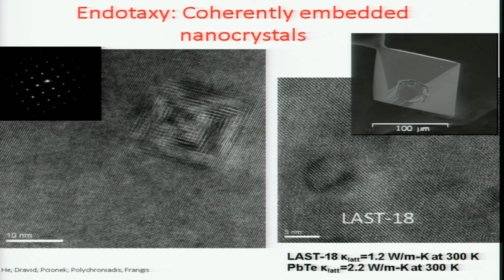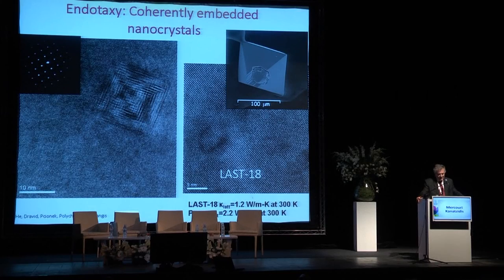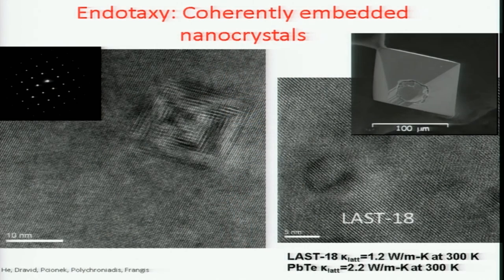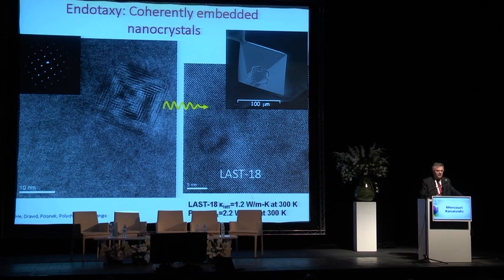Here you see a nanocrystal having precipitated and grown inside lead telluride, and that acts as the barrier for the heat. But you see how well the crystal is placed. We call it coherent or endotaxial with the rest of the matrix. And you see, if you take atomic rows in the matrix, you can go right through the crystal without changing atomic rows. It's very well placed and ordered. And that means if you're an electron, you can go through the nanocrystal just as well as you could go through the matrix. But if you're a wave, you can see this crystal. If the crystal is different in composition from the matrix, it must be different, then a wave of heat coming in, hitting the crystal, it's a different composition, it will scatter. And that would lower the thermal conductivity. But an electron coming in, seeing the nice coherently embedded nanocrystals, can go through. And that's how you can lower thermal conductivity without lowering electrical.